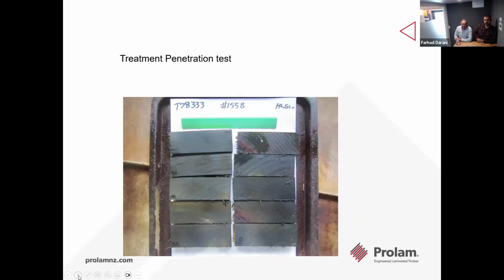And then that's our compliance report we get from IVS. For every 30 charges we put through, we have to do a sample test of 10 boards. So these all passed here, and the minimum we're allowed for chemical uptake is 0.75. So we always aim a little bit above where we need to be there.